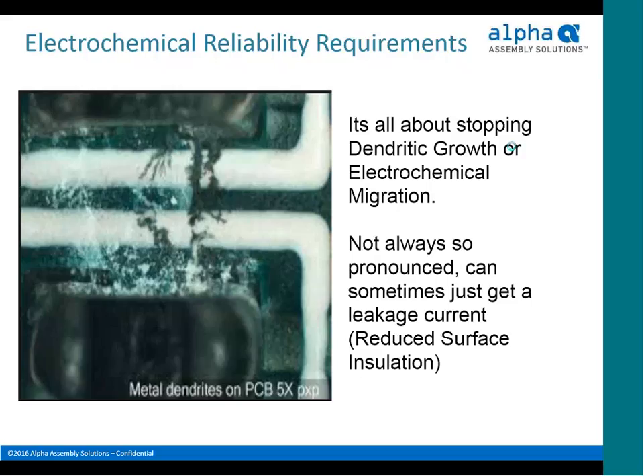In fact, much more common nowadays with current designs and current electrical performance requirements, we're seeing a lot higher instances where leakage current by itself is sufficient to cause failure of certain electrical circuits. So it doesn't necessarily require the obvious condition here, the dendrite, but the way we test for both of those conditions is the same. You'll see that as we go through some of the test methods.